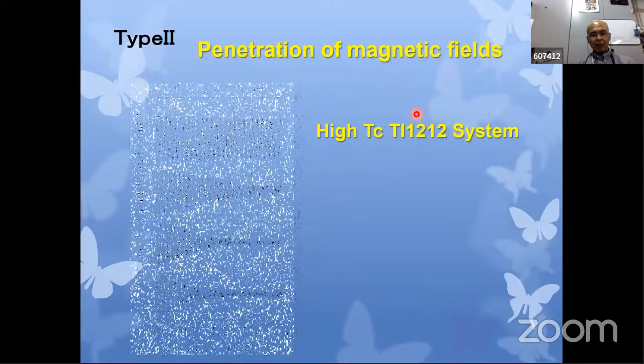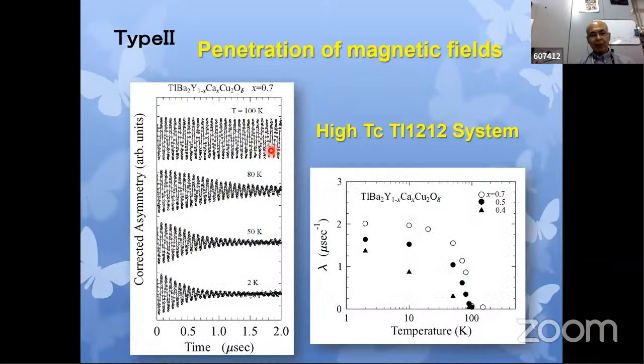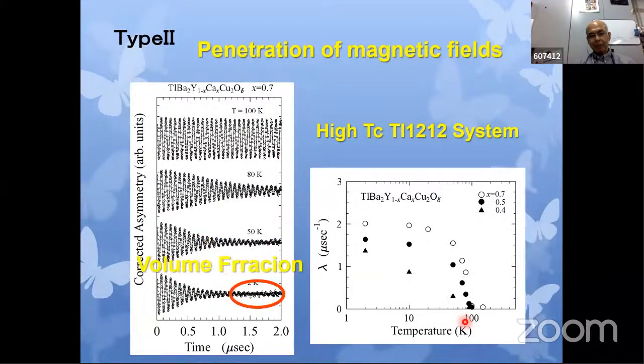On the other hand, this is my own data. This is also high TC data. In the normal state, we can see very nice muon spin precession like that. But in the superconducting state, the muon spin precession motion shows a large damping, just like a muon spin relaxation property appears. This damping becomes stronger with decreasing temperature. So this difference is caused by the superconducting state. The damping rate becomes higher and becomes like this. So this temperature dependence is also very important to discuss the superconducting state, because it completely corresponds to the density of the Cooper pairs, okay?